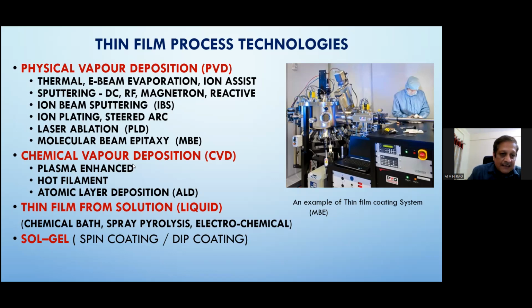So there are different ways by which you can impart energy instead of just heat energy from the substrate. You can impart energy by other means. You can use a plasma. You can generate a plasma environment so that the decomposition of the ions and gaseous molecules happens much faster because of charged particle bombardment, or because of the charged nature of the environment. The decomposition may happen at lower temperatures, or the reaction rate will improve if you use plasma enhanced CVD.